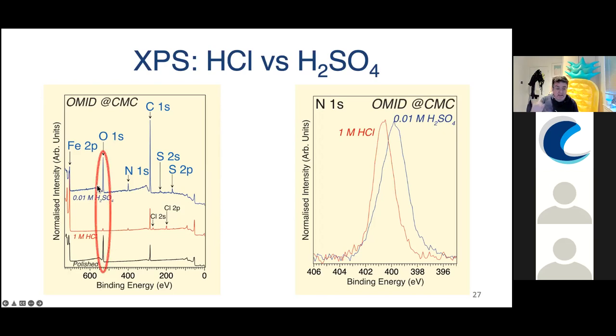For example, you can see a significant increase in the oxygen signal compared to the inhibited carbon steel in the 1 molar hydrochloric acid. And also you see a nitrogen signal again. In fact, it's a bit more intense in the sulfuric acid. If we look in more detail at the nitrogen signal shown here, I've normalized the heights, and I'm comparing the 0.01 molar sulfuric acid to the 1 molar hydrochloric acid. You see a shift in the binding energy of the peak.